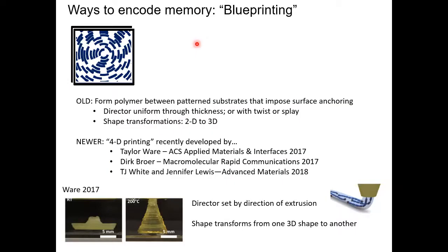So one way to do that is called blueprinting. The idea of blueprinting is that you take two pieces of glass and put a local anchoring pattern on the glass. That is a surface treatment that makes the glass align the liquid crystal along a specific direction. One way we can do that is to coat the interior surfaces of two pieces of glass, one in front of the other, with a material that can be oriented by polarized light. And then we can shine a thin beam of linear polarized light, like a raster across the cell, going left, right, right, left across the box, and put any pattern we want. In particular, we can put that bullseye pattern.